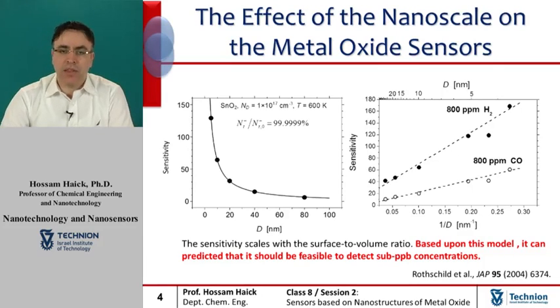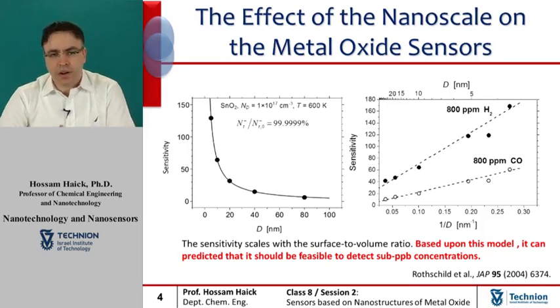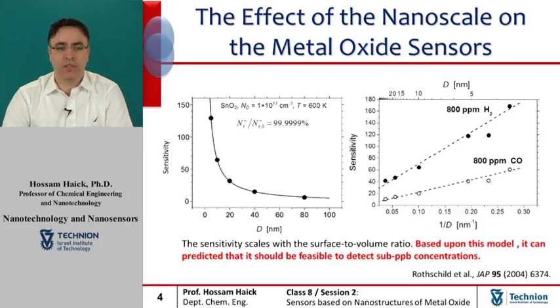Keeping in mind that much smaller signals can be measured and you can easily detect variations in conductivity at the single percentage level, you can realize that much smaller differences in surface trap densities are still detectable. So, the take-home message here is that nanosize sensors are extremely sensitive to gas-induced variations in the surface trap density.